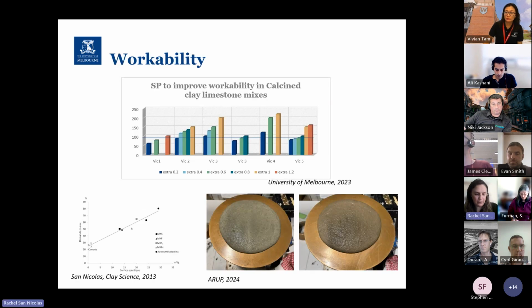I just want to touch on the performance in respect of workability, because I often have this question. What I want to say is, depending on the system that you are working with, you can improve the workability of a calcined clay system. Usually, if you are grinding the material too much, you will have too many fines, and it will be water hungry, and you will have to put a little bit more superplasticizer in your system. However, those are parameters that you need to control.